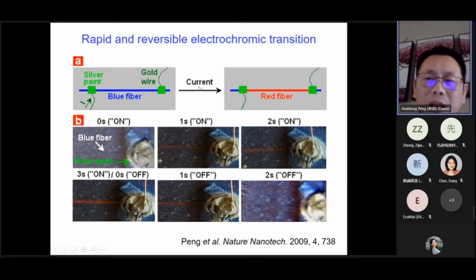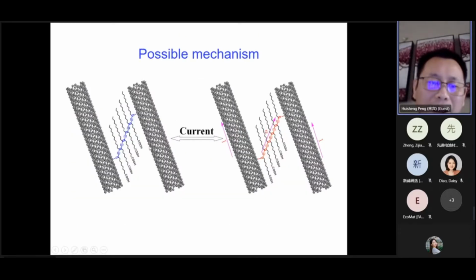We try to induce the color change based on the electric current, and we try to understand the mechanism, although it's still not very clear yet. Here's the carbon nanotube, and here are our polar diacetylene molecules. As you know, when you pass an electric current, the carbon nanotube is conductive, so it will form an electric field. The electric field will induce the side chain. We designed these polar groups in the side chain to induce the conformation change of the backbone. Therefore, the electrons on the backbone undergo the transition to pi star, and they will absorb different wavelengths of light, and therefore macroscopically we will observe the color change.